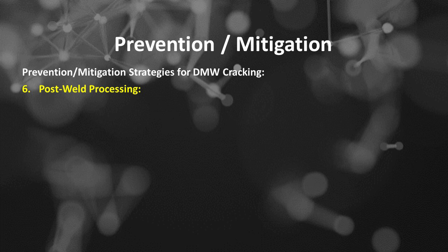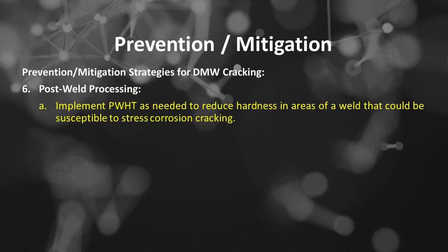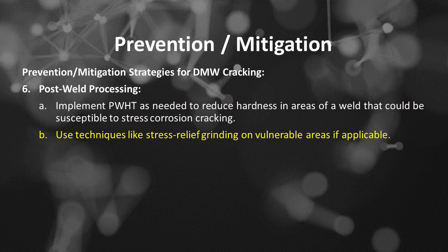Include: the first is implement PWHT as needed to reduce hardness in areas of a weld that could be susceptible to stress corrosion cracking. The second is use techniques like stress relief grinding on vulnerable areas if applicable.